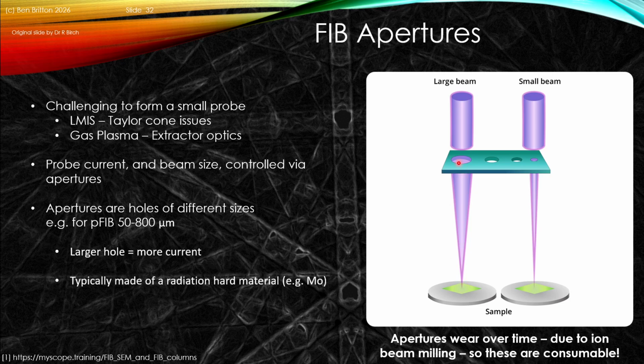Now, why is this important to note? Well, these apertures, this incident beam, will hit the aperture and can wear this aperture over time. So, due to ion beam milling of the aperture strip, the apertures themselves are actually consumables in a FIB-SEM instrument. And that's super important to bear in mind because, for instance, the current for a particular aperture, if the instrument is not well maintained, might drift over time. There are a series of different aperture sizes depending on the specific setup. If you want to get into this discussion, I'd suggest that you talk to your manufacturer about more details. And these are larger hole to give you more current, and they're typically made of a relatively radiation hard material, something like molybdenum or tungsten in that mix.